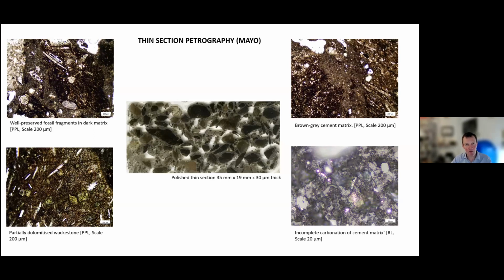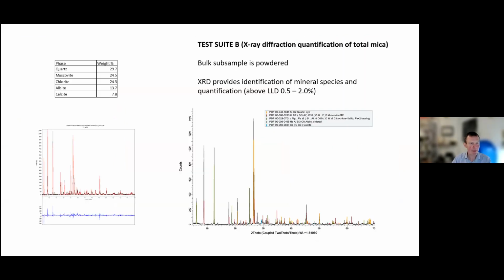It's important for the pyrite type material that we make a thin section, because a lot of the pyrite that is particularly problematic is very fine grained, and we can see it in the bottom right. The scale bar on that is 20 microns, so 0.02 of a millimeter, and you can see that the little bright grains of pyrite are really small, maybe less than a micron, many of them.